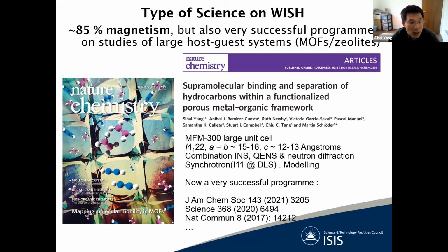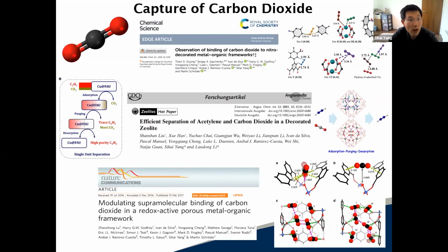So the whole idea started in 2014, where I illustrate this example here. That is a MOF system with a relatively large unit cell, about 3,000 cubic angstrom. So we did a combination of inelastic neutron scattering, quasi-elastic neutron scattering, and neutron diffraction to resolve the host-guest interaction that rationalizes the separation properties. And today, this has become a really very successful program indeed.